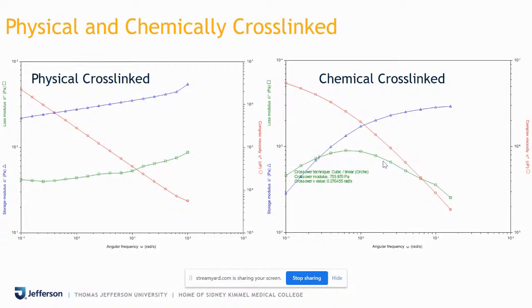So the physical cross-link hydrogel system has a classical signature. If you run a frequency sweep experiment, because this is an angular frequency on the x-axis, we term this experiment a frequency sweep experiment. At any strain value, if you keep on increasing the strain or reducing the strain, these two lines will never meet each other.